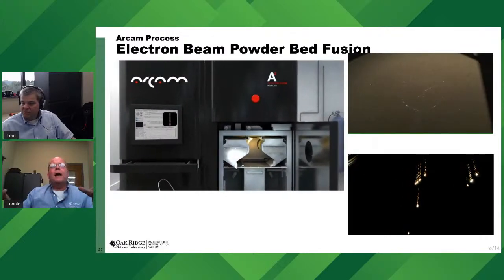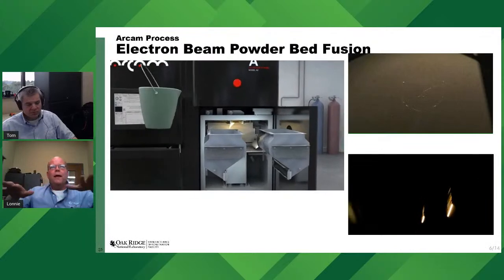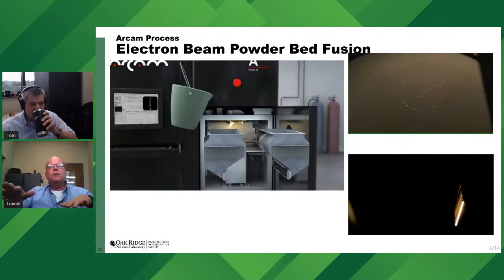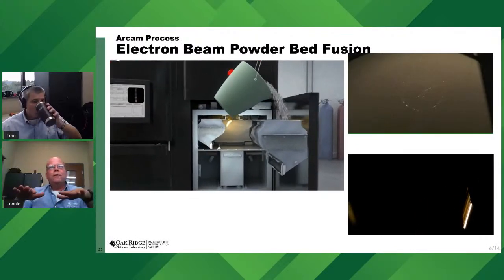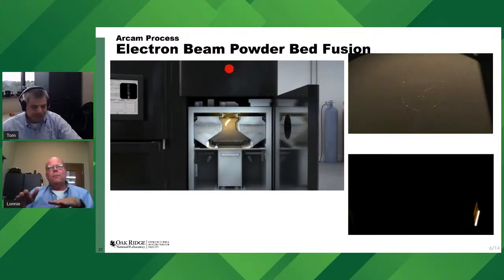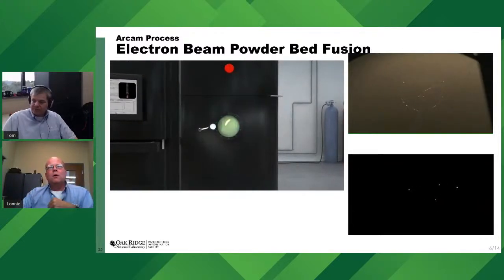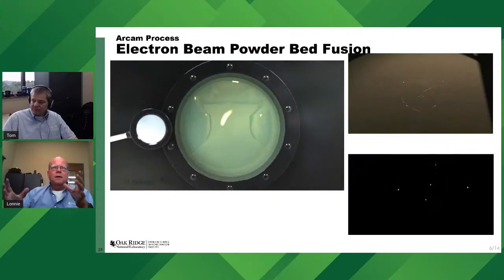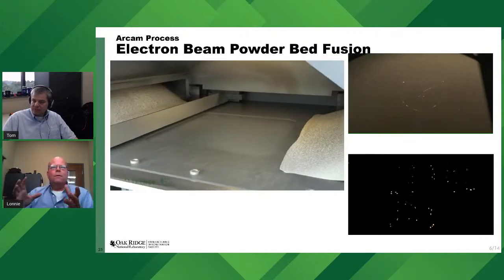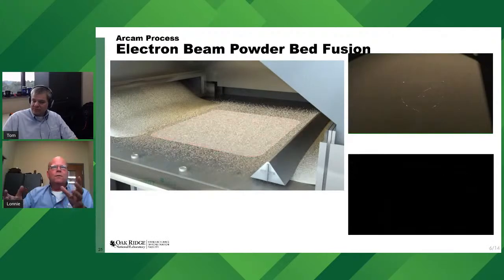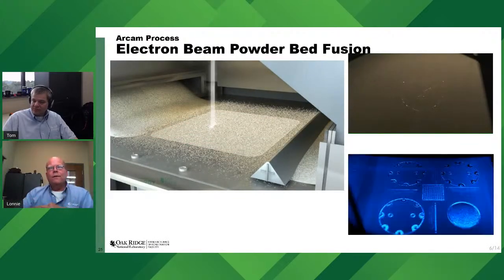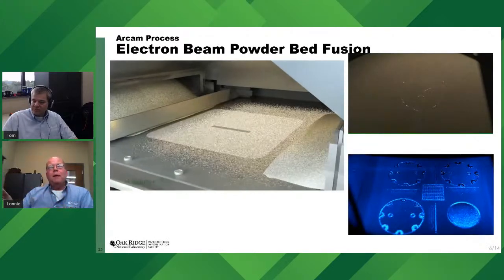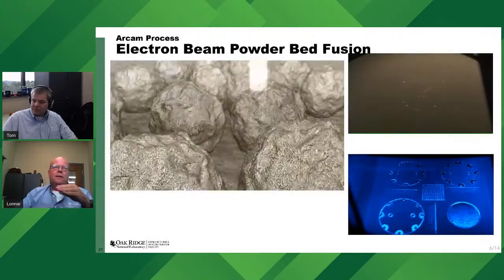The heat is spread out. You're able to move that energy around and spread the heat out evenly, so your residual stress is usually very low. They preheat the powder bed. On most laser powder bed systems, the powder that's not melted never usually gets over maybe 100 degrees C, 150 degrees C. With the E-beam, it's like 600 degrees C, 700 degrees C.